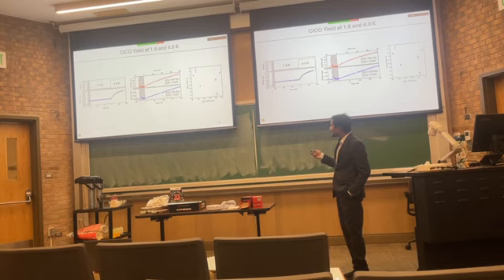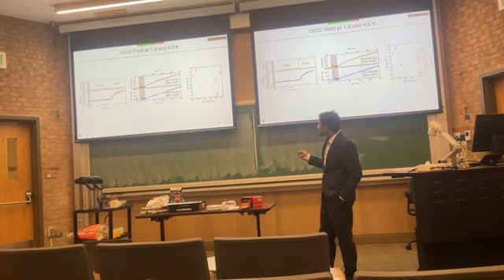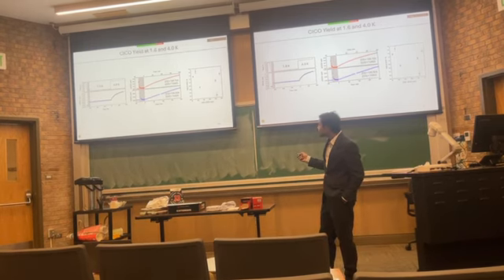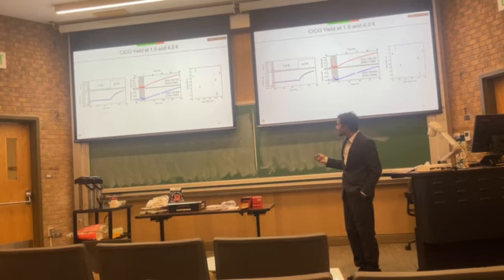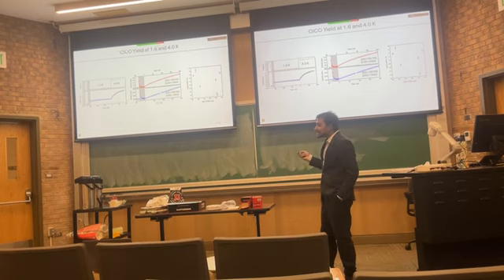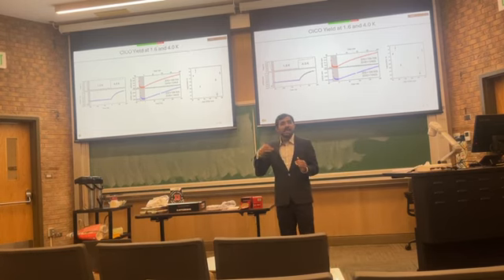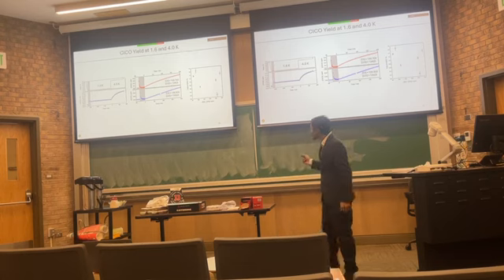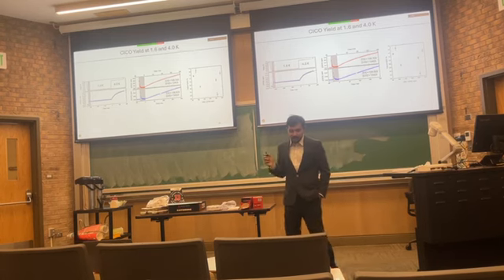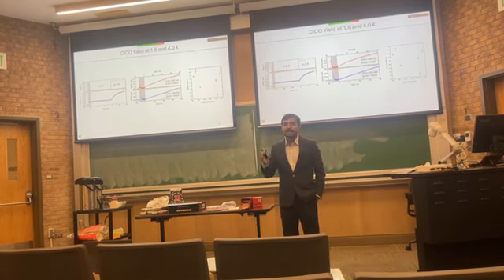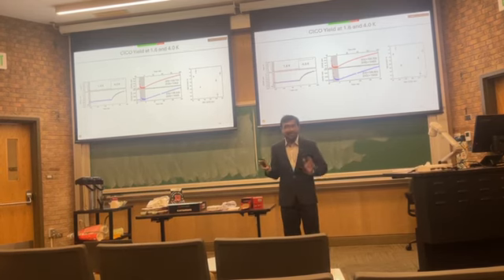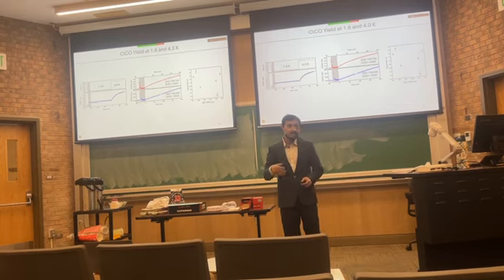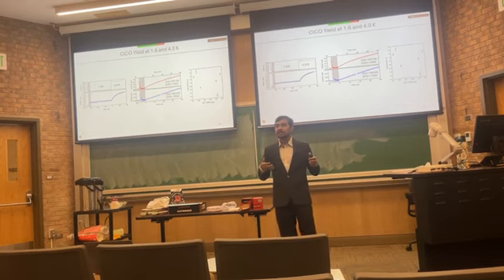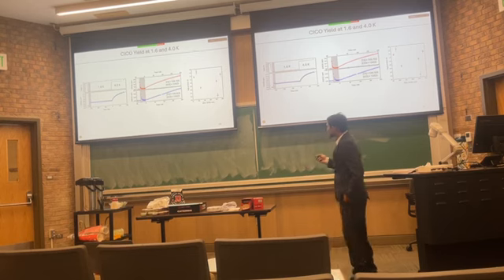So let's look at all the yields. Those red ones are the high temperature yield, which averages about 1.2%. But at low temperature, the yield is like 0.1% or 0.15%. So our yield at high temperature is 10 or 15 times higher. That tells us that at high temperature, this reaction has better yield than at low temperature. But that's not very surprising. Whoever does chemical reactions knows that if you increase the temperature, sometimes yield goes up.